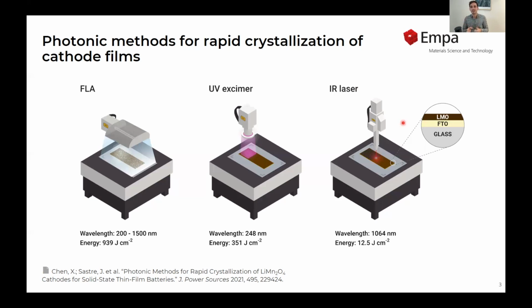Another technique that we investigated is UV excimer laser. This is a commonly used technique in the semiconductor industry for photolithography, for example, and it's a UV laser emitting at 250 nanometers, more or less, that is capable to deliver energy densities in the order of 300 joules per square centimeter. And lastly, we also tried to use an IR laser, which is, for example, commonly used for scribing, which has a wavelength of 1064 nanometers, but it's capable of delivering much lower energy densities, only about 12 joules per square centimeter.